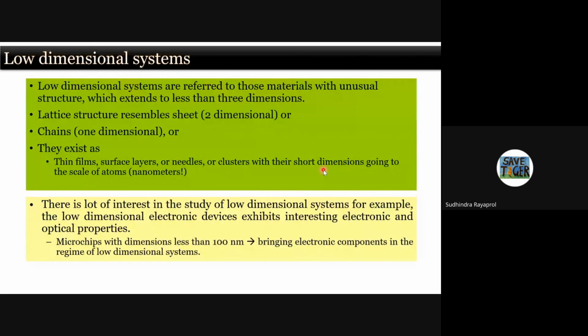So in most of these low dimensional systems, mainly because of this type of triangular lattices or topological reasons, you can end up with a frustrated ground state or magnetic ground states which are not completely zero, but they don't exhibit long range magnetic order either. There's a lot of interest in studying low dimensional systems because electronic devices exhibit very interesting electronic and magnetic properties, because if you look at microchips which have a dimension of less than 100 nanometers, the electronic components can go to these low dimensional regimes. So you don't see long range magnetic order, but there is a small magnetic component which has a net zero component.